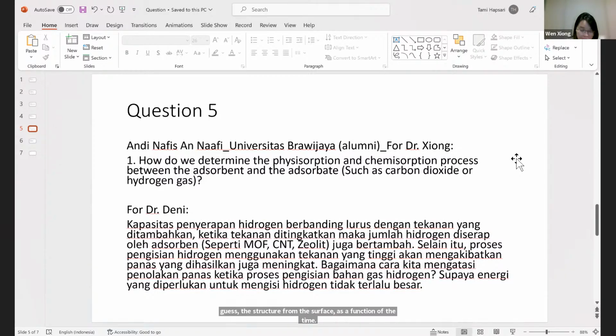Generally, we divide the physisorption and chemisorption desorption temperature at about 100 degrees C. If CO2 or hydrogen desorbs from the surface at a lower temperature, for example from 0 degrees C to 50 degrees C, we would say that's physisorption. If CO2 or hydrogen desorbs at a high temperature, like 100 degrees C to 150 degrees C, then we say that gas has been chemisorbed on the surface. So those are 2 ways you can determine physisorption and chemisorption.